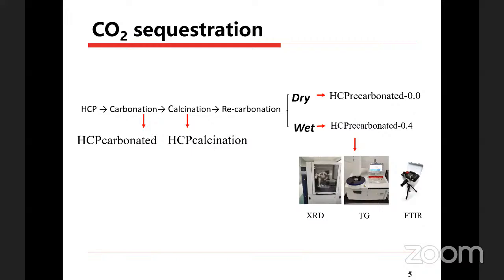First, in this study, we try to investigate the role of water in the process of carbon dioxide sequestration. So we try to use two types of water content. One is without any water added. The second one is where we use a powder to water ratio of 0.4, and we use several analysis methods to investigate the carbonation phases formed and the carbonation degree.